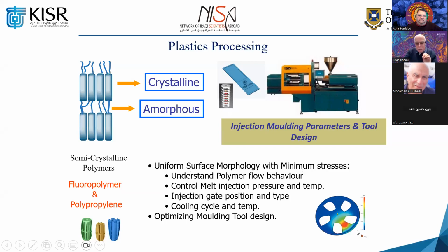It has minimum stresses. You don't want to have any stresses, because when you do the grafting, there is an accumulation of polymer grafted to the surface when there are cracks or stresses. So try to really make the surface pretty uniform. Of course, we have to understand the polymer flow behavior in order to design the conditions in the injection molding to produce a perfect material with uniform surface.